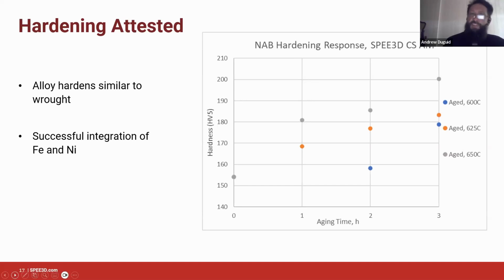That's more or less what we expect from the published data on this alloy. That's great. We've achieved a hardening reaction. We can now dial in the strength of the alloy where we need it, based on modifying the aging treatments. And as I say there, the iron and the nickel must be participating in that reaction. Otherwise, it wouldn't be hardening in that way. Okay, we move on to the next slide.